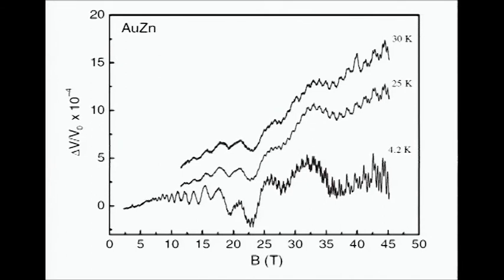So this is the speed of sound in the material, and this is the magnetic field, and you can see the quantum oscillations extend to 30 Kelvin in this picture, but I later measured the sample to higher fields in a pulsed magnetic field.